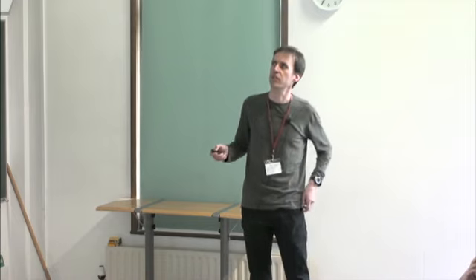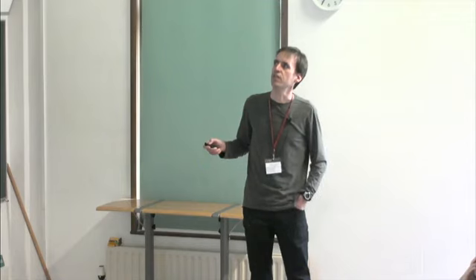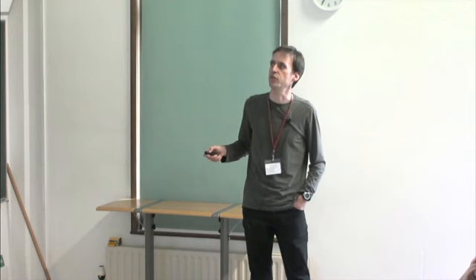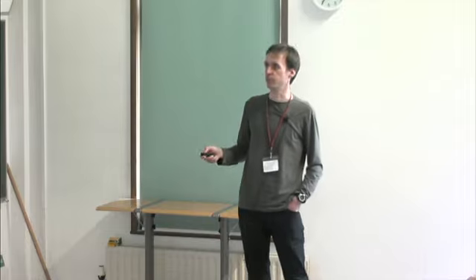So if you take some of them positive, some of them negative, then you end up with a frustrated system, of glassy character. It turns out that in such a system there is no net ordering, so the global P2 remains equal to 0, but below some temperature there's some local frozen-in ordering, like a glassy ordering. And this nicely reflects also in the NMR spectra, because here instead of two well-resolved lines, we have a so-called Pake-type powder pattern.